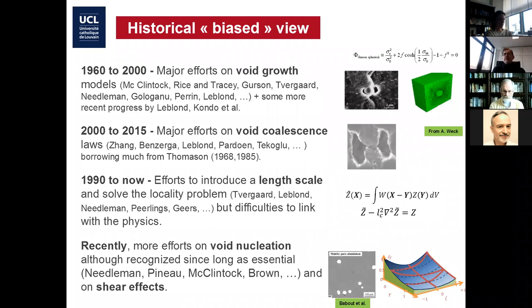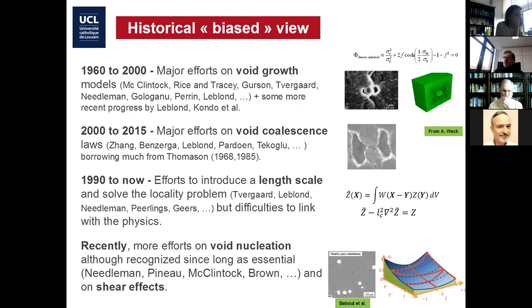Let me give a quick historical view on how the community has addressed this failure phenomenon from a micromechanical and microstructure viewpoint. From the 1960s to probably the year 2000, the focus of the community was on understanding the growth of the void — not focusing too much on nucleation or coalescence, but essentially the growth process. There were a lot of efforts by McClintock, Rice and Tracy in the late '60s, the famous Gurson model, etc., to model the growth process and predict how void radius and volume fraction evolve with plastic deformation for different loading conditions including plastic anisotropy and rate effects.